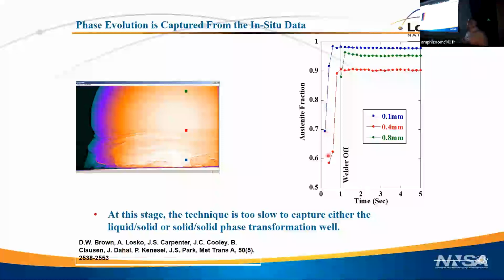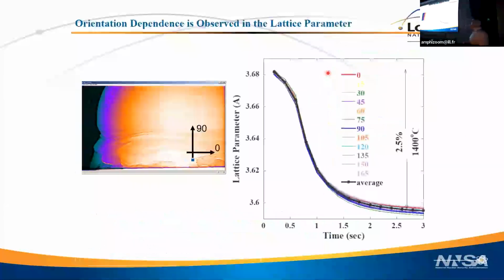We get it when it's about 60 or 70% austenite, and then it, quite quickly, here are my units of seconds, right? So within one measurement point or two, these measurement points are separated by 1/10 of a second, we're up to pretty much fully formed austenite, where you would expect it to be about 95% of the volume fraction. You'd expect a residual ferrite of about 5% in this material. So we can, in some sense, measure that solid-solid phase transformation, but clearly we don't have enough resolution and time resolution to really say we've monitored the solid-solid phase transformation, and we've completely missed the liquid to solid phase transformation.